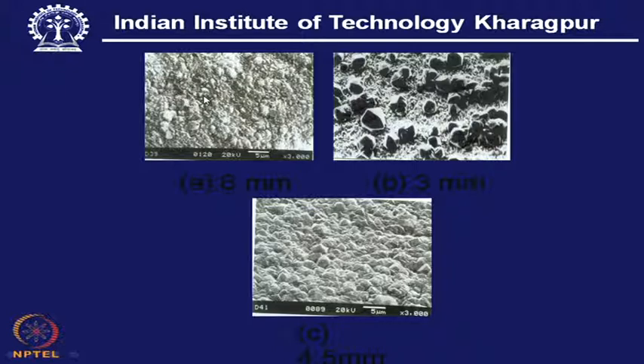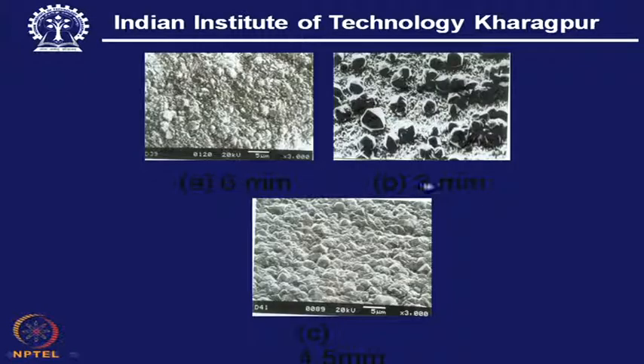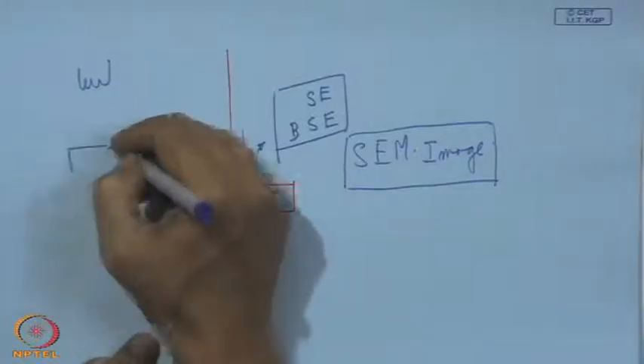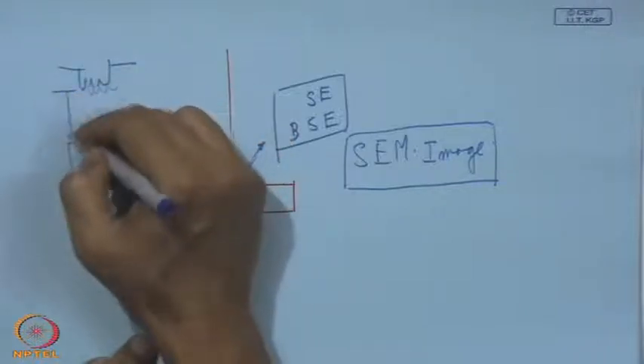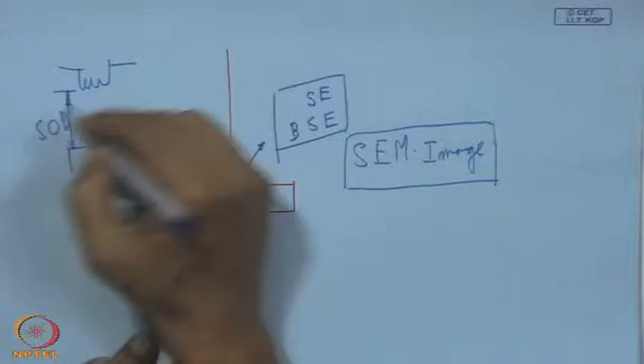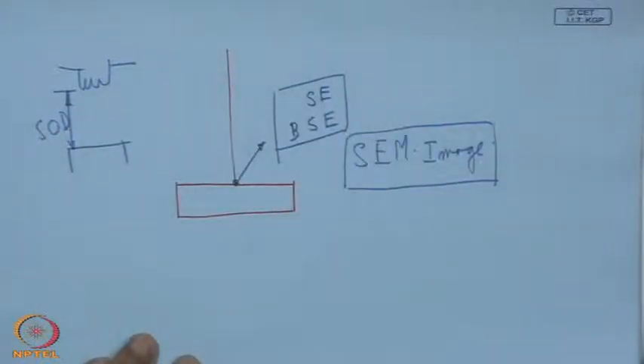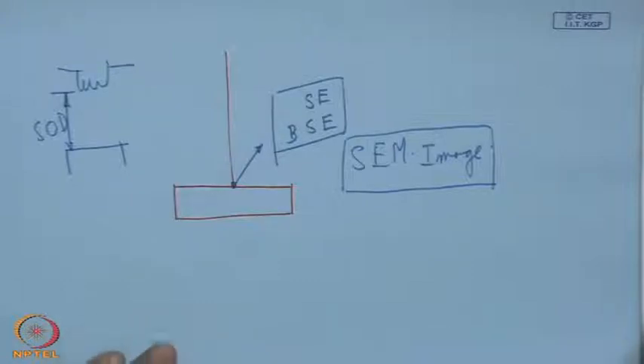And we know there are certain process parameters in diamond coating, and one is the distance from the hot filament to the substrate, this SOD, which is 6 millimeter, 3 millimeter and 4.5 millimeter, and if we vary that, we have different results. For example, just a quick look, this is the filament and there is the substrate, if we recall, and this is SOD. So, this experiment gives us a clear indication that with 3 millimeter, it is so delicate, and this delicacy can be understood just by the image produced by SEM.